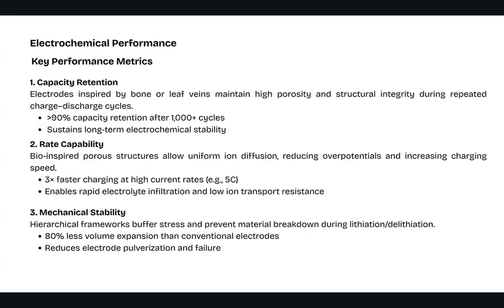So electrochemical performance. The key performance benefits or metrics are, first, capacity retention. Electrodes inspired by bone or leaf veins maintain high porosity and structural integrity during repeated charge-discharge cycles. So there's greater than 90% capacity retention after even 1,000 cycles, more than that, in fact. So it sustains long-term electrochemical stability.